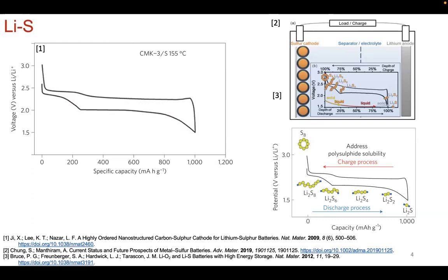Well, if you thought you weren't going to produce Li2S until lower voltages, you could just reduce your voltage window so that you form these longer lithium polysulfide chains so that they're dissolvable, and you can maybe trap them in some way, versus just having Li2S fall out and deposit on the cathode. That affects how you engineer your catholyte.